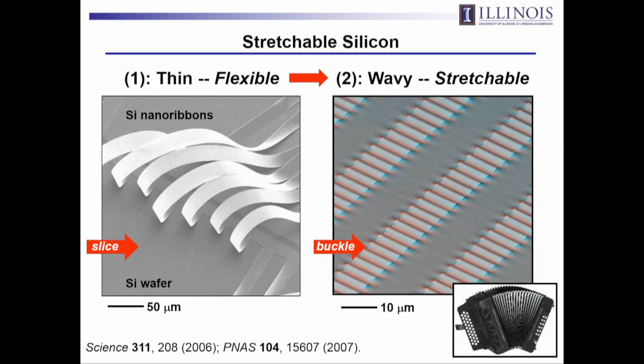The first idea is that any material has a bending stiffness that's defined not only by the intrinsic modulus of the material, but its overall thickness. That's just Newtonian bending mechanics. In fact, the flexural rigidity decreases like the cube of the thickness. So if I go from a silicon wafer, which is a millimeter thick, and I figure out instead how to shave off very, very thin membranes from the surface of that silicon wafer, I can render a form of silicon that's flexible and floppy, as illustrated here by these silicon nanomembranes. They're about 100 nanometers thick, so much thinner than the silicon wafer. We figured out how to do this from a material standpoint, and you can slice them off at thicknesses that are still sufficient to support all the electronic functionality you want. So make the silicon thin, it becomes flexible.